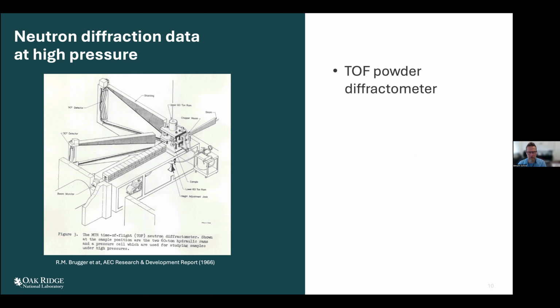It is a time of flight powder diffractometer, which at the time was completely new. This was not the first ever powder diffractometer, but it was one of the first ones. And they deliberately exploited the time of flight technique because it allows you, as I'll talk about in a bit more detail later, to pull out a full set of diffracted intensities with a very low angular coverage of detector.